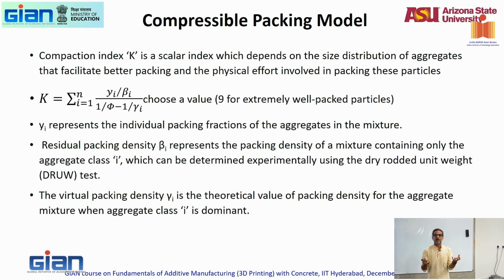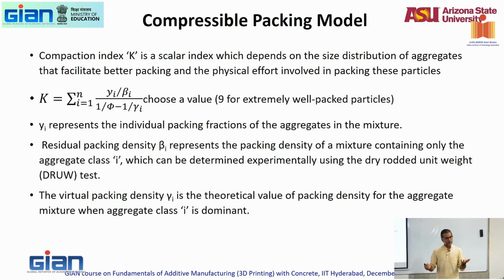So if I take well-rounded, really rounded aggregates, and I try to pack a volume, assume that's number 4 aggregates, really, really rounded for argument's sake. I'm trying to pack number 4 aggregates into a cylinder. How much can I expect my maximum packing density to be? I gave you the number a little earlier. No, this is number 4 alone. 0.74 maximum, right? So if you do the experiment and get the answer as 0.78, you better go back and redo the experiment. You're wrong. It clearly says you're wrong, unless the aggregate is really angular. But generally, you know what kind of upper limit you're looking for, correct?